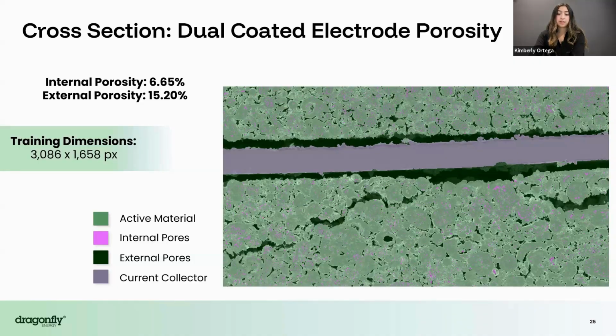Then a neural network was trained by manually labeling these regions of interest and teaching the model what each class looks like. Once trained, the model can then be applied to the entire dataset and automatically label every single image slice with these 4 classes. This process is very beneficial as it reduces the amount of manual time and effort required for image analysis, especially for really large datasets. So from this segmentation model, we calculated that the internal porosity was about 6.65% and the external porosity was about 15.20%.